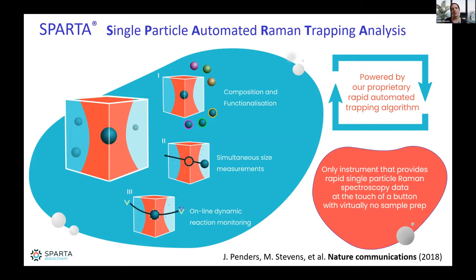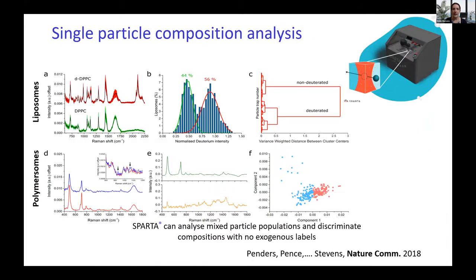And so this enables us essentially to measure chemistry within single particles that you would never normally be able to distinguish if you were performing a bulk measurement. And so you can really pull out heterogeneity that you wouldn't normally be able to. And you can see what the prototype instrument looks like in the top right there, but I'll just show you a couple of things that we can do with it.